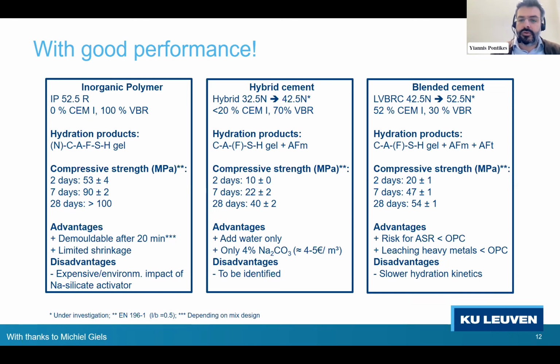Blended cements, also very good, more than 50 megapascal in 28 days. Usually people are reluctant about the early strength, but I think it's decent, and it can of course even be enhanced, because in the blended cements and the hybrid cements, plasticizers do work. So if you have access to PCs, please give them a try, and you will see that things will go upwards with respect to performance and perhaps with respect to durability.